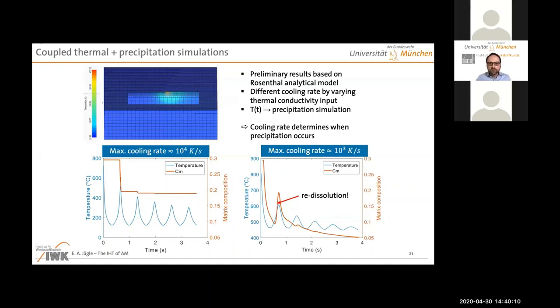So here is not even FEM. This is a simple analytical model, often applied to welding, the so-called Rosenthal model, which has an analytical solution. It's just a point-like heat source in a semi-infinite plate, moving with a constant velocity, and we just take these Rosenthal peaks and stick a bunch of them together, and generate some kind of semi-realistic time temperature profile. So don't look at the details, but already please look at the orange curve. The blue curve is the time temperature profile. And the orange curve is the output of our kinetic model, initially fitted kinetic model, where we feed this blue